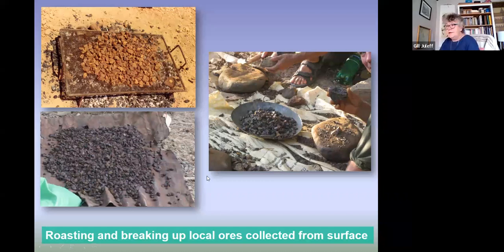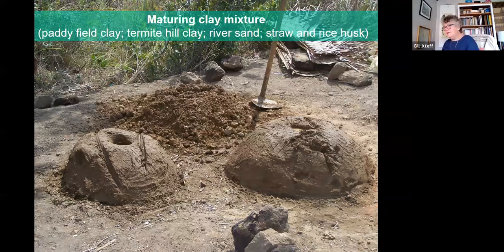The other thing which is important and tends to get forgotten is the clay used to build these furnaces. These furnaces have to operate well over 1,000 degrees centigrade. This clay has to resist those temperatures. It has to remain standing. So the container for iron smelting is extremely important. And with the help of our local villagers at Samanullaveva, we put together a very complicated mixture of paddy field clay, termite hill clay, river sand, straw, rice husk, which was very, very carefully mixed and matured to build the furnaces.